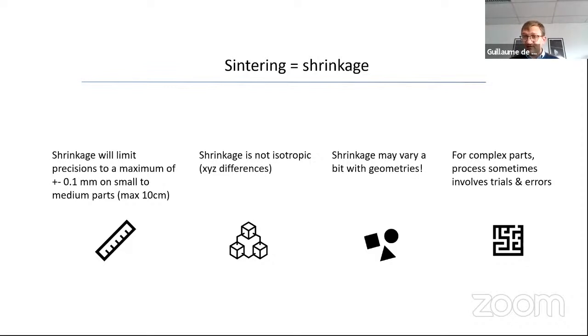The second thing is usually shrinkage is not isotropic. So X, Y, and Z are usually different. You may say, okay, that's acceptable. We just have to have the shrinkage factor for X and Y and the shrinkage factor for Z, which is definitely something we would agree with. The other problem, and that's really more problematic, is that shrinkage may vary a bit with geometries. So you won't have the same shrinkage for, say, a pyramid, a cube, or a cylinder.